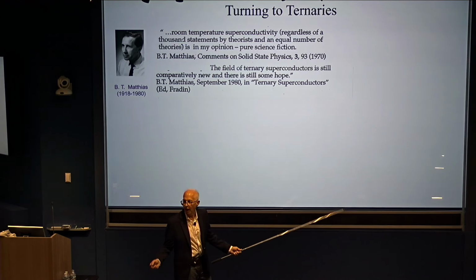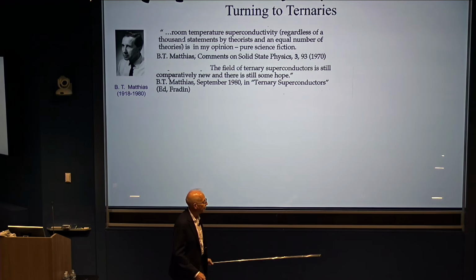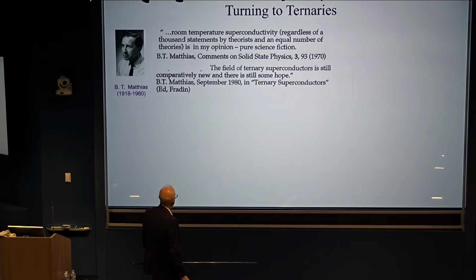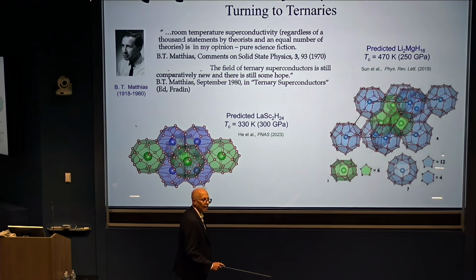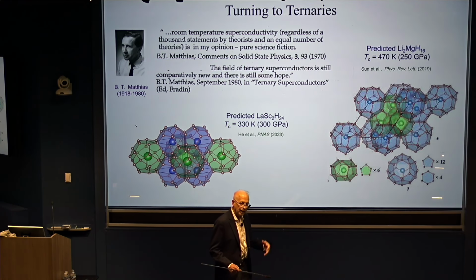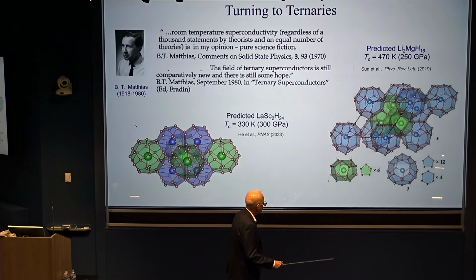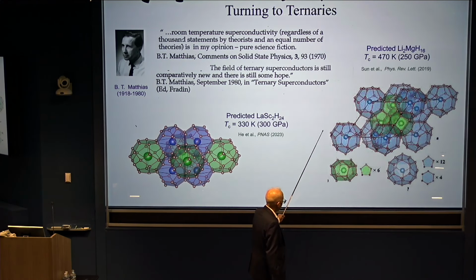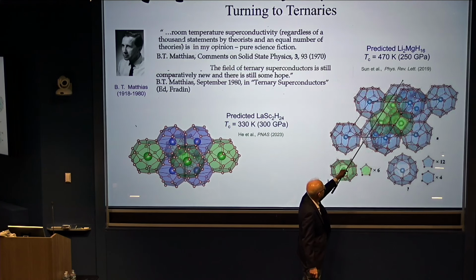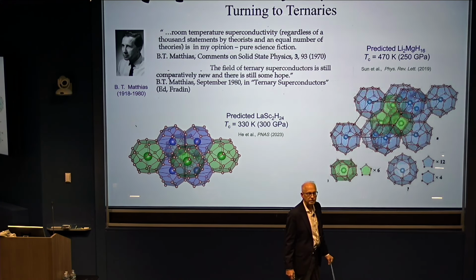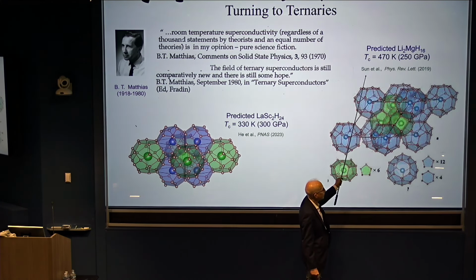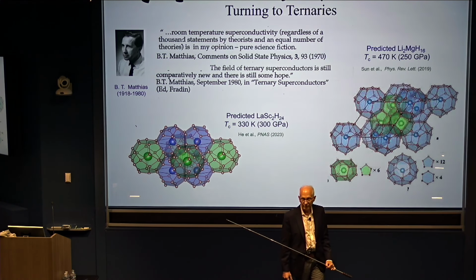Now, he wasn't talking about hydrides at that point, because the hydride superconductivity was not yet developed, but those were interesting words of wisdom. And now we see a new era where we're looking, at least theoretically, at much higher temperature superconductors. This is an important prediction by my colleagues at Jilin University in Changchun, China, and they, back in 2019, predicted this combination of lithium, magnesium, and hydrogen could have this astonishing hot superconducting temperature of 470 Kelvin.